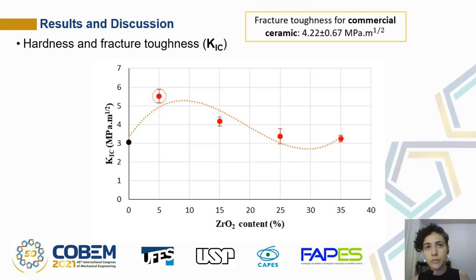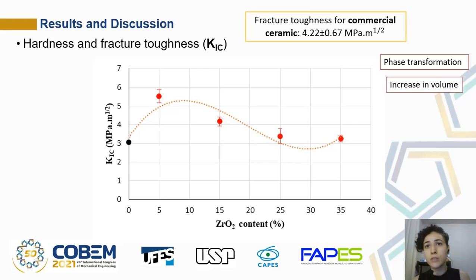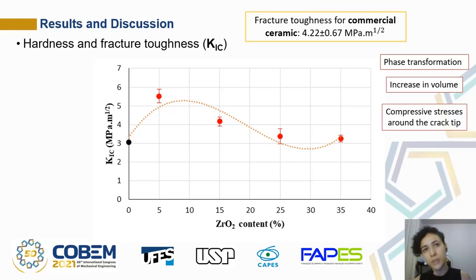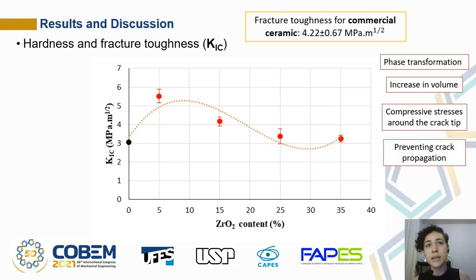The improvement of this property is due to the phase transformation of zirconia from tetragonal to monoclinic phase. This phase transformation is accompanied by an increase in volume which induces compressive stress around the crack tip, preventing its propagation and developing the toughening effect. However, for the 5% of zirconia sample, some porosity level might have been able to absorb fracture energy, changing the fracture mode and increasing the toughness.